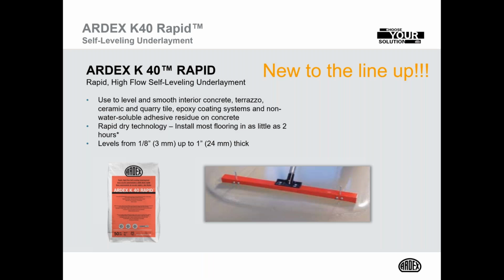Compressive strength on this is crazy. You're over 8,000 after a month. But the cool thing about it is, with this rapid strength development and the ultimate strength that this product has, my thought was it was going to have a lot of tension, a lot of pull as it's curing. And this product does not have a lot of tension at all. So it's a newer technology, lower tension product, but it's self-drying and you're putting flooring on it very quick. It's also a high flow product, so we can use it at an 1/8 inch thick as that blotter layer I was talking to you about a few minutes ago. So both the K10, the K40, the K60, all can be applied at an 1/8 inch thick, over mitigation systems for that blotter layer application.